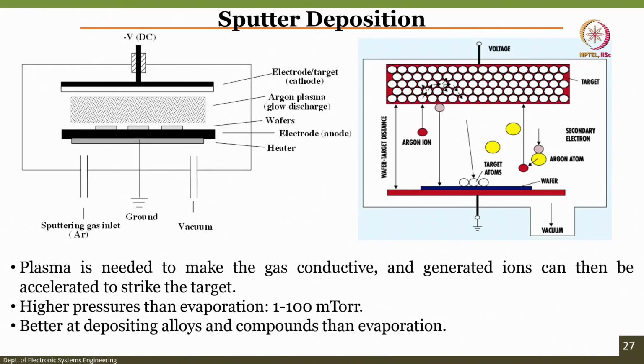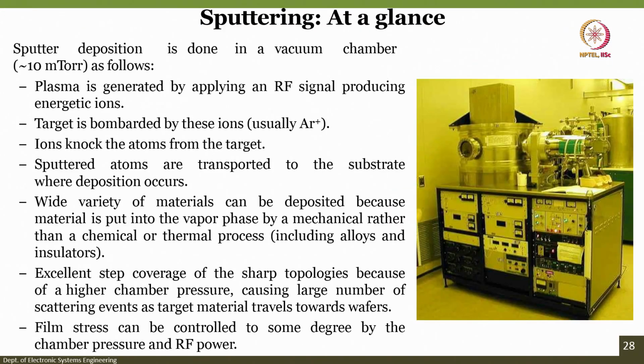As you see in the slide, this is a clearer image of how the plasma is needed to make the gas conductive, and generated ions can then be accelerated to strike the target, right. You can see here the target is here and the argon ions are bombarding, and the target atoms are dislodging, right, and then forming the film on the substrate. So, higher pressures than evaporation, about 1 to 100 millitorr, better at depositing alloys and compounds than evaporation. In evaporation, you can still deposit alloys, but sputtering is better compared to evaporation techniques.